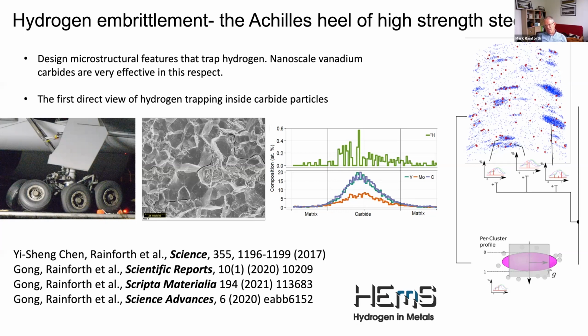Now, the good thing about the steel that we developed is that vanadium carbides, particularly the very fine coherent ones, are very good at trapping the hydrogen. So if you do get hydrogen ingress into the material, then particularly the semi-coherent, slightly larger precipitates are very efficient at trapping hydrogen. And so the deficit in strength from hydrogen embrittlement is far, far less than it is with some of the competitor materials such as dual phase steels and so on, where the deficit can be much larger.